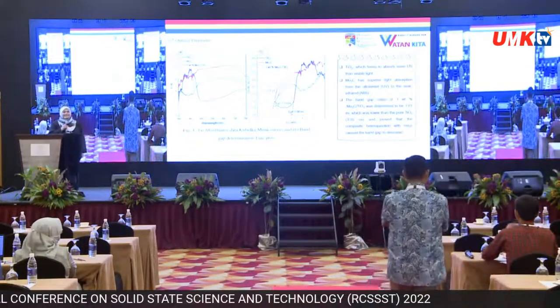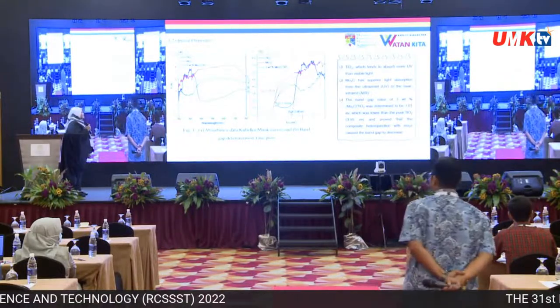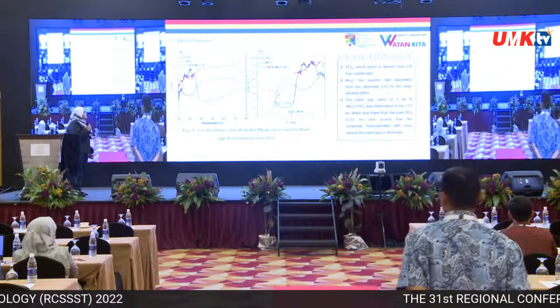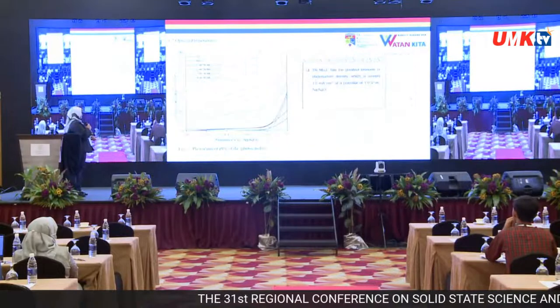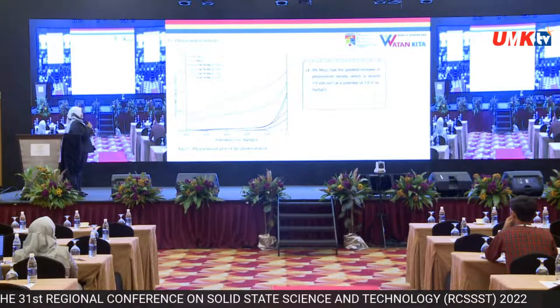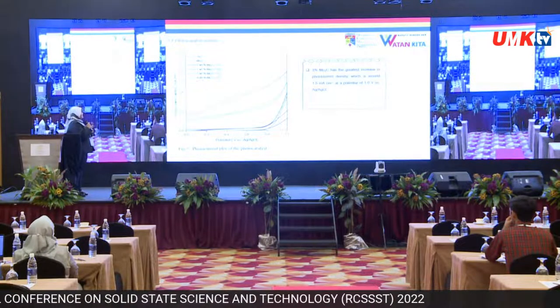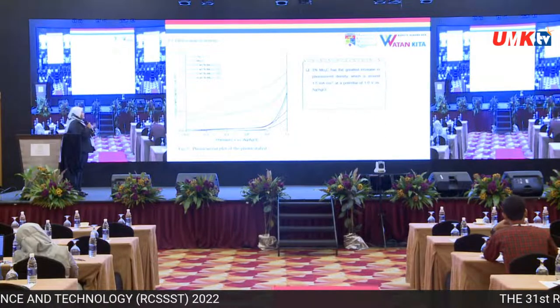Okay, thank you. Any more questions? I have one question. Why are you using the concentration of molybdenum 3%? What happened if you increase the concentration? I've been trying 1, 2, 3 and 4%. Based on the photocurrent measurement, the 3% has the highest photocurrent. This is the method that I optimized to choose between 1, 2, 3 or 4%. The 4% has reduced the photocurrent.